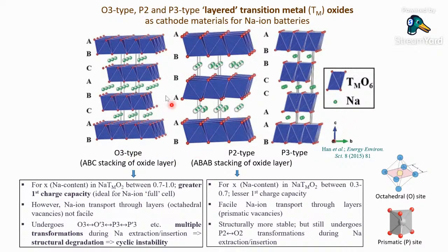Now, these are the two types of structures that have been looked into as cathode material for sodium-ion battery, with some work on P3 type structure also going on. The advantage of the O3 type of structure is that it can start with a sodium content of 1 per formula unit, that one can synthesize it and achieve a stable O3 type of structure with a sodium content of 1 per formula unit. Whereas for a P2 type structure, usually a sodium content of less than 0.7 leads to the P2 type of structure. But this is disadvantageous because the cathode material is supposed to be the reservoir of the alkali metal ion in an alkali metal ion cell. So that way the O3 type of structure is advantageous. Though a lot of work is now underway, including in our group, trying to stabilize P2 type structure at higher starting sodium content. But that's a different story, and I won't be discussing that today.